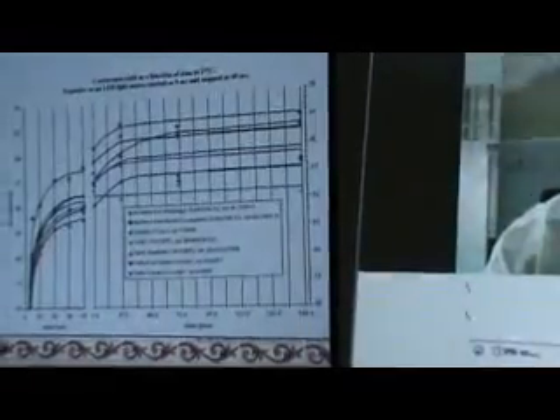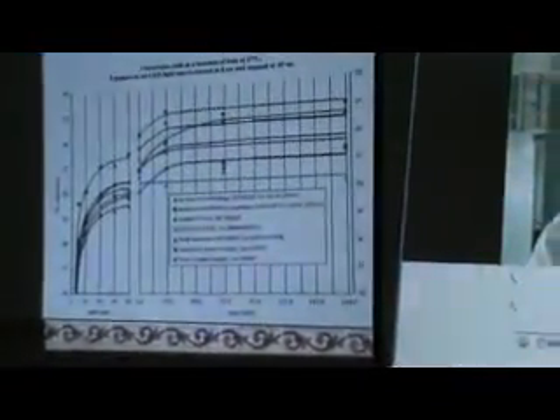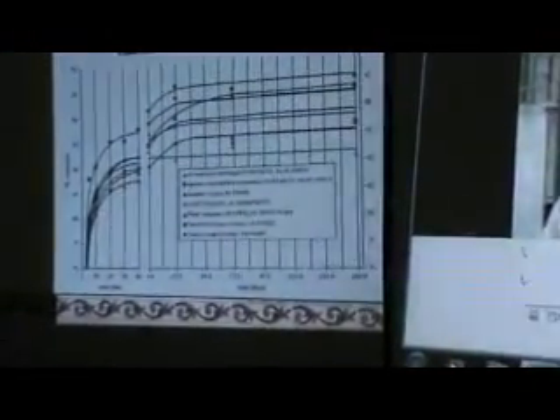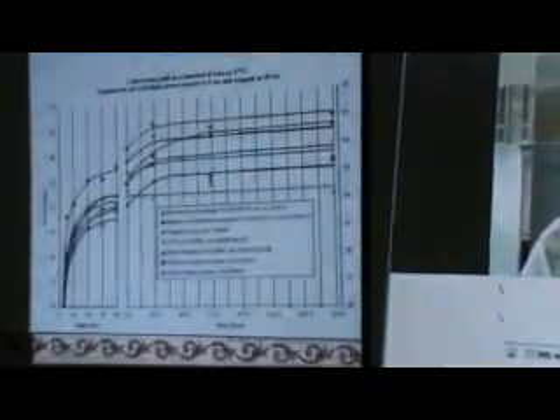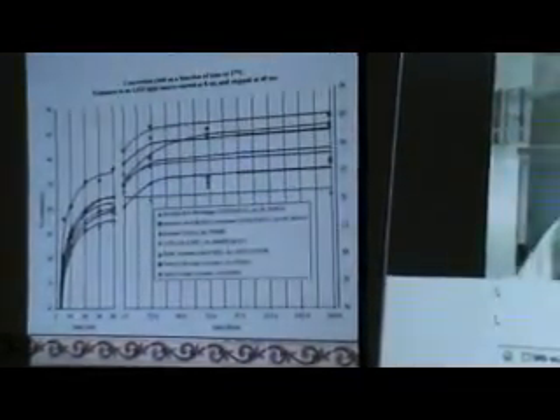take the light away. And in this graphic on the right side, you see the result from 1 hour to 169 hours. Here you can see that, for example, for microhybrid, you have about 56-57% of conversion rate after 40 seconds, but the process continues, and after 1 hour you reach 62%, and after 25 hours you are at about 66%. So this is the same for all products. You have first the conversion rate which goes very fast, and then it becomes more and more slow, but it continues for about 25 hours.